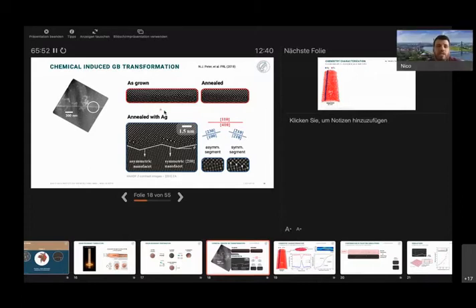Oh, maybe I should add. Go ahead. For the grain boundary, that becomes a little bit more tricky, because if the two zone axes are not exactly met, then basically all the structure of one side disappears, and then you cannot make any guess anymore of the structure. Yeah, one side becomes clear and the other doesn't. Yeah. Exactly. So this is something you need to make sure of, that the two zone axes are parallel to each other by less than 1 degree.